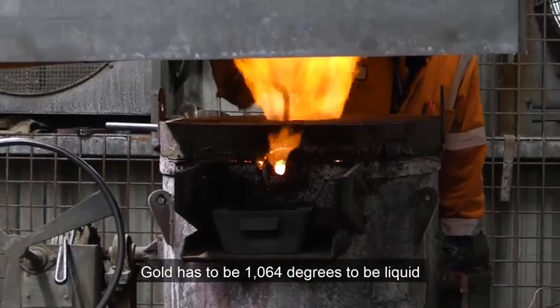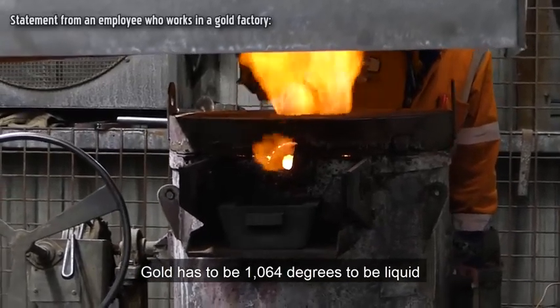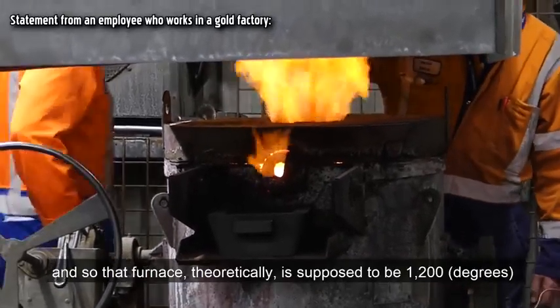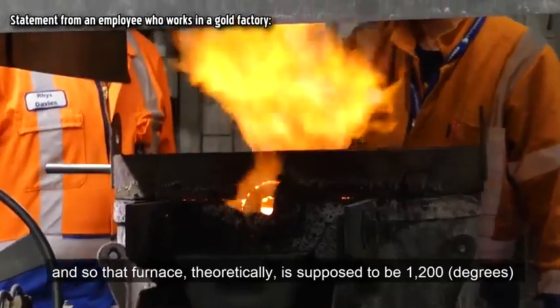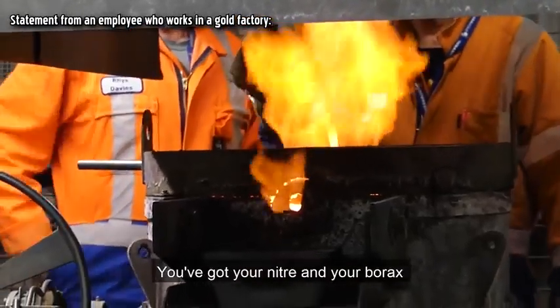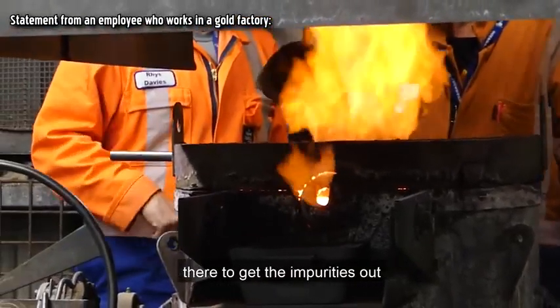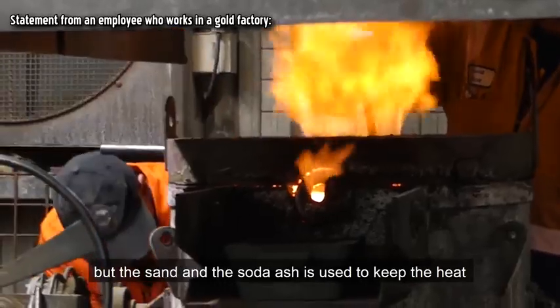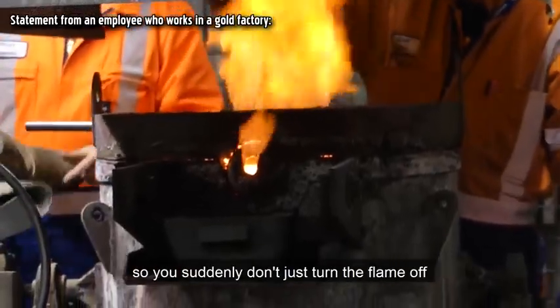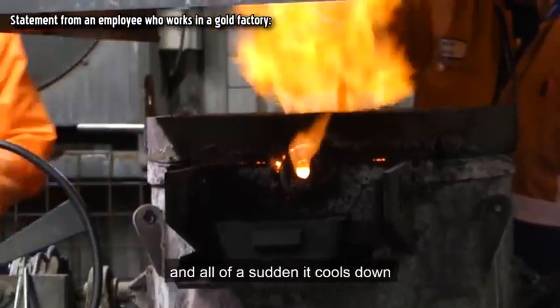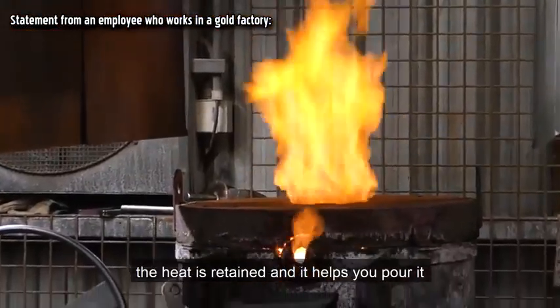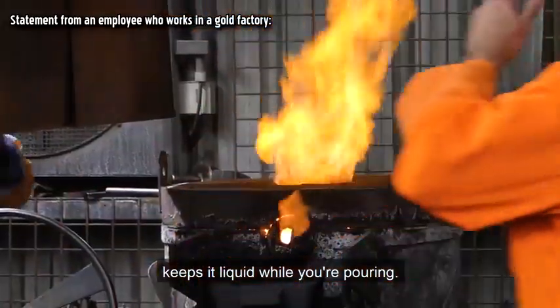Gold has to be 1064 degrees to be liquid, and so that furnace, theoretically, is supposed to be 1200 degrees. You have got your niter and your borax there to get the impurities out, but the sand and the soda ash is used to keep the heat. So you don't just turn the flame off and all of a sudden it cools down, the heat is retained, and it helps you pour, it keeps it liquid while you are pouring.